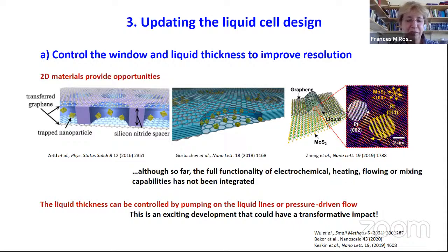It's been clear from our discussion of resolution that if you want good images, you want to have great control of the window thickness and the liquid thickness, as well as all the microscope parameters and the electron beam effects. But let's see what we can do in terms of engineering the window and liquid thickness. So one way, of course, is to use 2D materials for windows. So here's graphene stuck on both sides of a silicon nitride spacer to make very small enclosures for reactions. This type of experiment so far hasn't been that good for electrochemistry, because we really want to be able to flow our liquids, heat them up, put an electrode in there, have a full circuit, and that's more difficult with these complicated liquid cells. But another way of controlling the liquid thickness is by changing the pressure, because we are pushing the liquid in with a syringe pump.